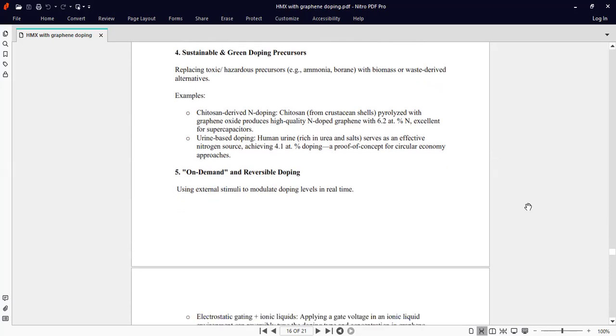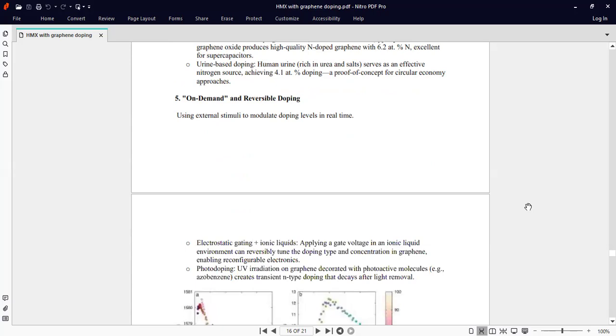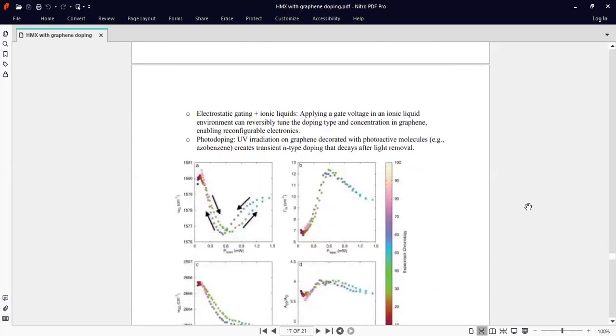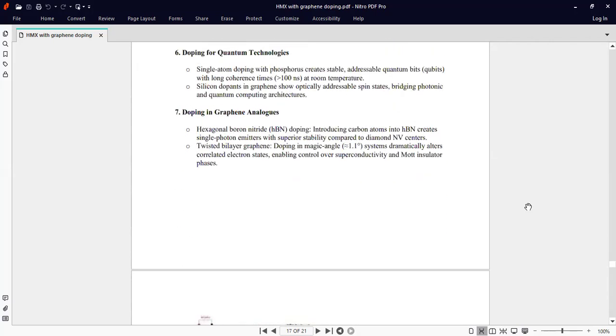On demand and reversible doping, using external stimuli to modulate doping levels in real time. Electrostatic gating and ionic liquids: applying a gate voltage in an ionic liquid environment can reversibly tune the doping type and concentration in graphene. Photodoping: UV radiation on graphene decorated with a photoactive molecules, e.g., azobenzene, creates transient n-type doping.